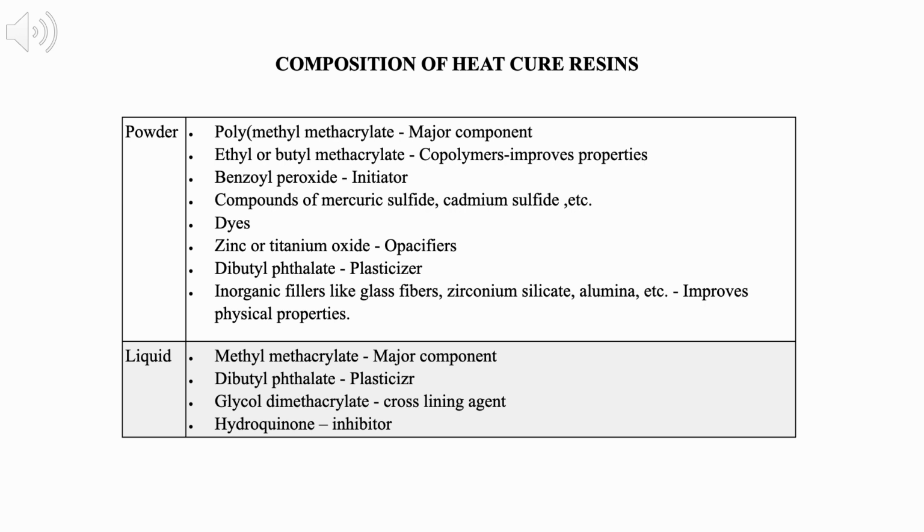improves physical properties. Liquid. Methyl methacrylate, major component. Dibutyl phthalate, plasticizer. Glycol dimethacrylate, cross-linking agent. Hydroquinone, inhibitor.